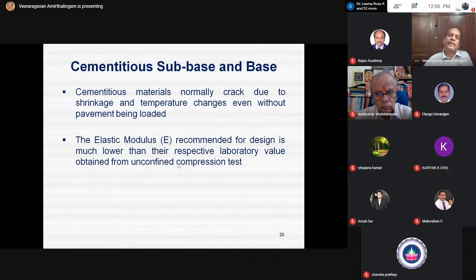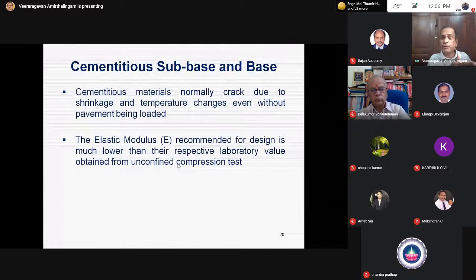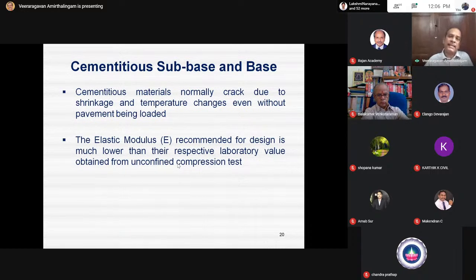What value? Again, when you want to predict the performance, you have to predict the performance in different phases. Phase 1, phase 2, and phase 3. In phase 1, modulus may change from 5,000 to 4,000. For phase 2, it may change from 4,000 to 2,000. Phase 3, it may change from 2,000 to 1,000. So you have to consider a stepwise deterioration model rather than having a single model for 15 years or 20 years.